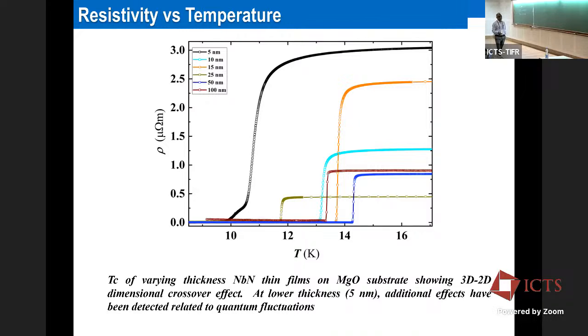14.7 Kelvin. And now our interest was somewhere here, where you can see some quantum fluctuations taking place at this particular thickness, because we are reaching the thickness of the coherence length, which I was telling you. The coherence length was around 5 nanometers. So we are having a thickness of around 5 nanometers. So the quantum phenomena are very much prominent in here.